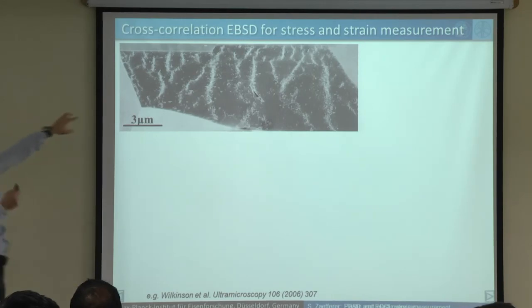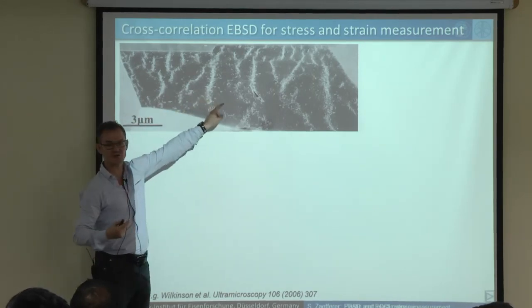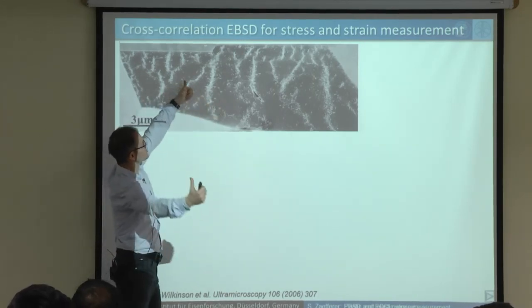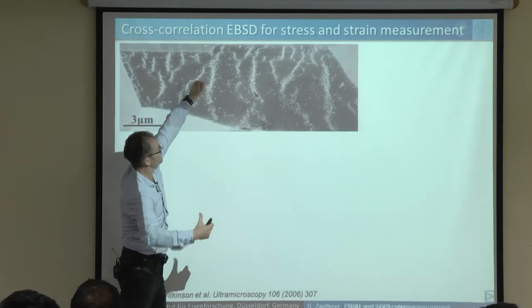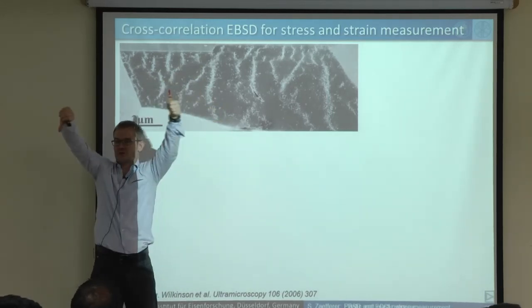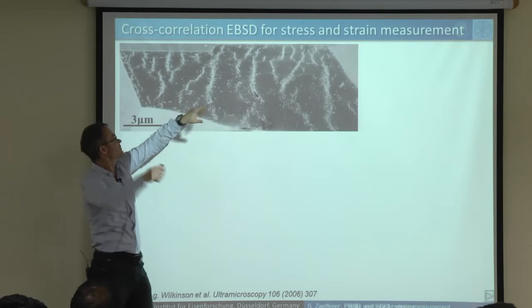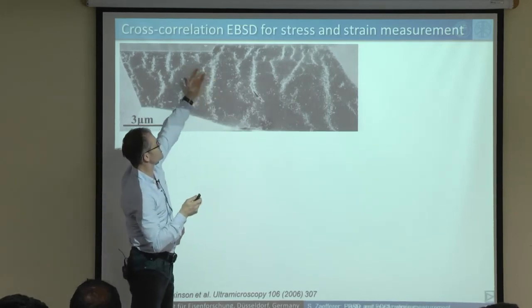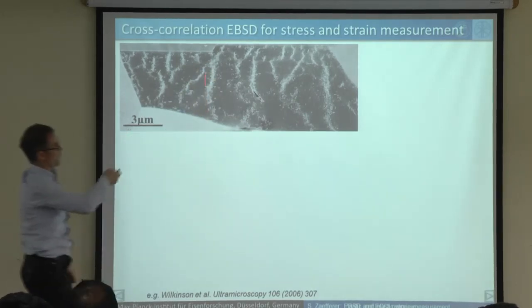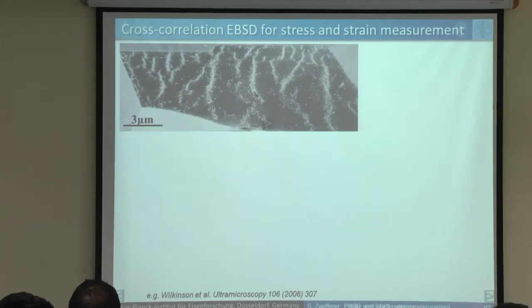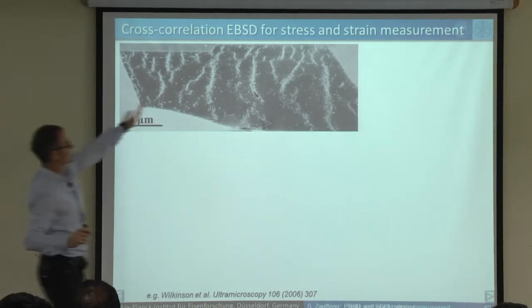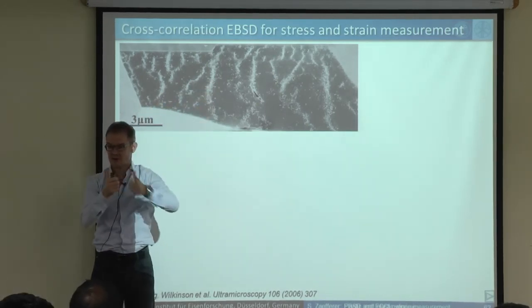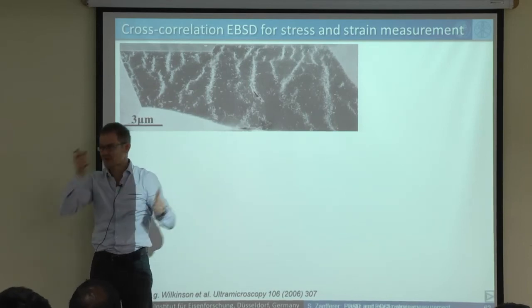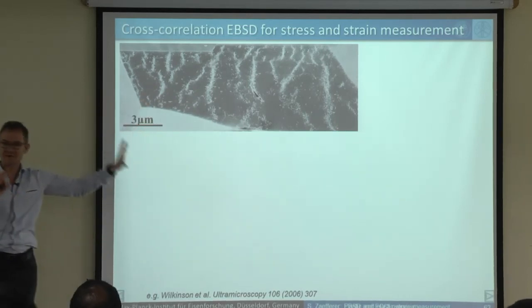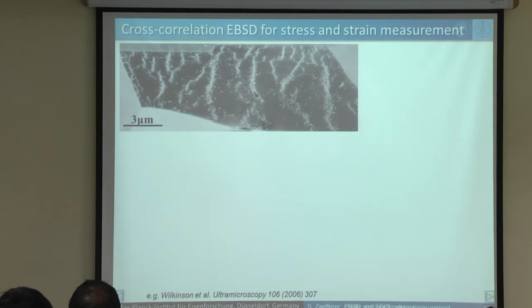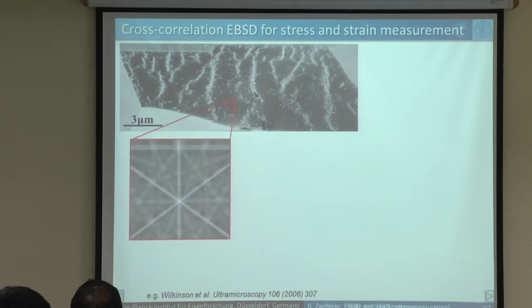And these dislocations which are in the walls consist of dislocations of two types. On one side they come from one side, and on the other side they come with a different sign. So you will see different rotations on either side of these walls if you do EBSD across it. And you will also find that in the middle of that wall, the residual stresses get very high. So there's quite a complex arrangement of stresses and strains inside of such fatigued structures.